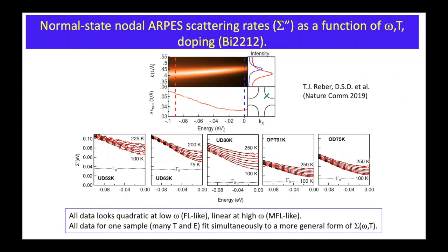At low temperature, there's lower scattering rates, or lower sigma double prime, or lower momentum widths. So you take the momentum width, you multiply by the bare Fermi velocity, and you get sigma double prime. All of this is in the normal state, because I don't want to worry about the effect of superconductivity. I'll do that in the next set of slides.